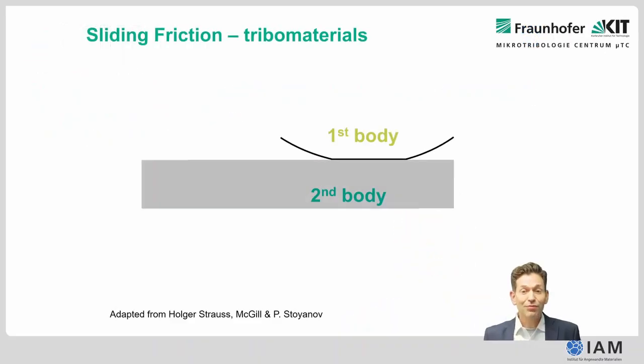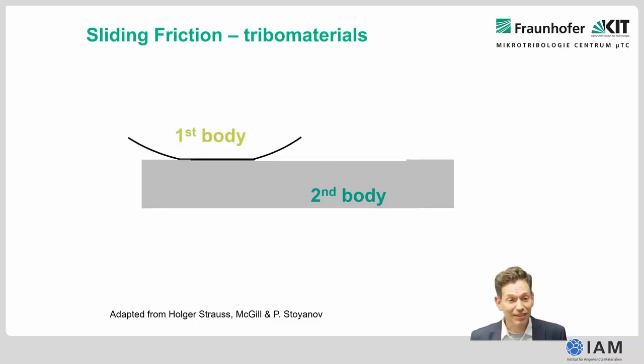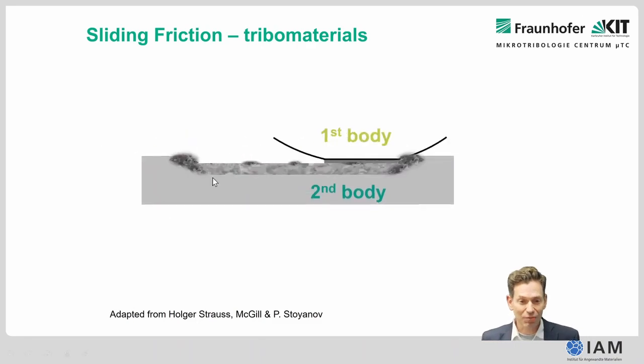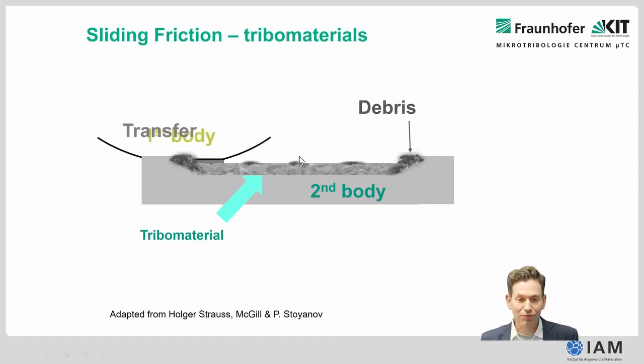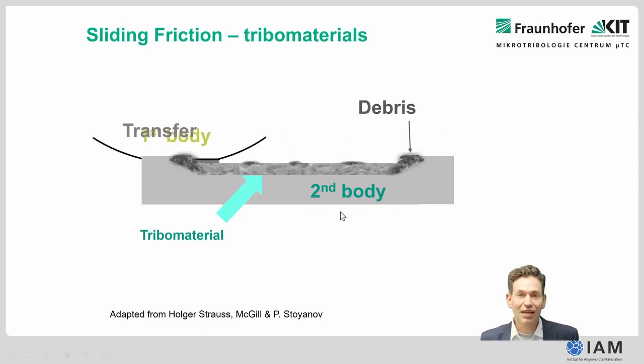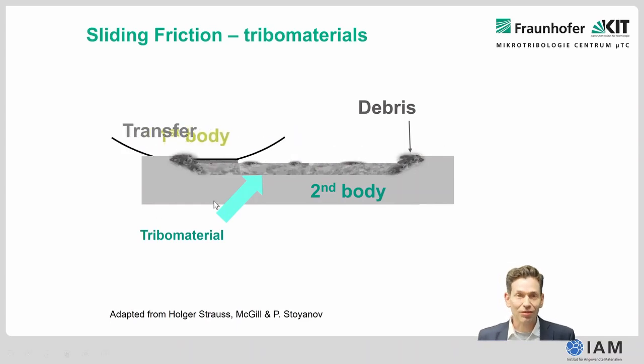When you have two materials in contact with each other and sliding on top of each other — a first body and a second body in reciprocating motion as shown in this schematic — we see a lot of effects happening. Usually we have structural transformation of the near-surface material, transfer from one body to the other, and we form wear particles and debris. All these effects together lead to the formation of a new tribomaterial, sometimes also called a third body.